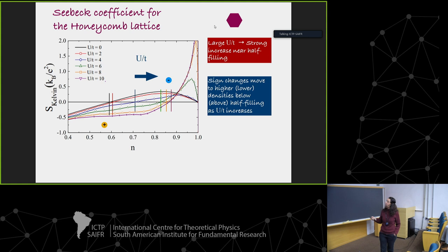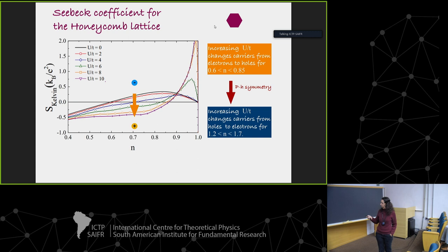For the honeycomb lattice, we see something similar. Once again, as we increase correlations, the crossing points move, this time towards higher densities. As a matter of fact, they both move toward densities close to half filling. In this case we see the effect the other way around: as we turn correlations on, we move from electrons to holes. I'm only showing half here, but as we are in a particle-hole symmetric case, the same occurs in densities above half filling, 1.2 to 1.7, where we will see an increase and not a decrease, going from